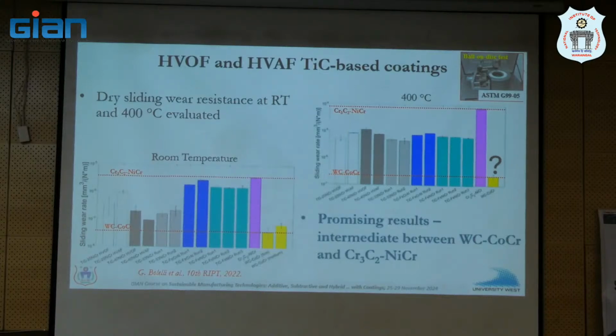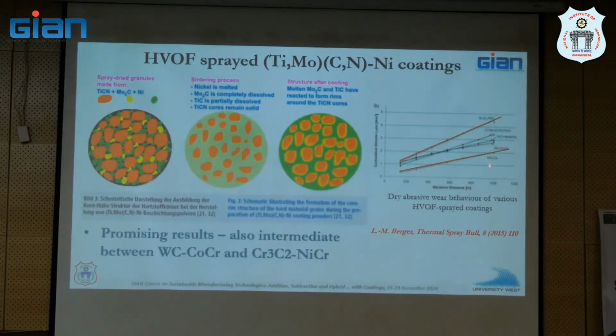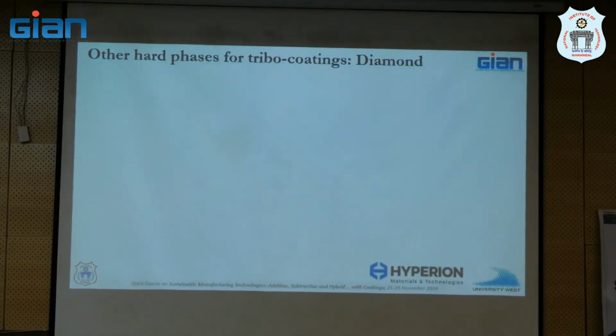So we have looked at titanium carbide by a couple of prominent techniques here, and we always get a performance which is kind of halfway between the two popular materials that I showed for wear, tungsten carbide and chrome carbide. It's somewhere in between. Yeah, and there are a lot of results out there which consistently show the same outcome. Yeah, titanium carbide is very nice and gives you something in between those two. A couple of years ago, actually during COVID, we started an interaction with Hyperion. It used to be part of Sandvik, but they have become separate now. And they are a company that makes grinding media actually, right? They have nothing to do with thermal spray, right?